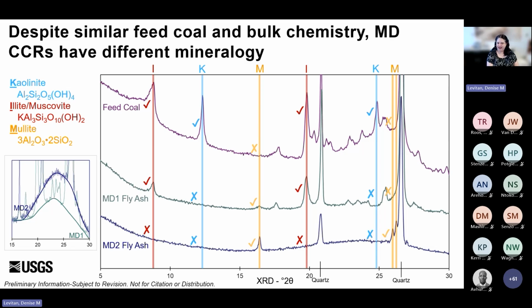So if you look at the blue Ks here and here, I marked with checks and X's whether those peaks are present or absent in each of the diffractograms. So looking at the kaolinite, you can see in the feed coal those two peaks are very clearly present. But then if you look down in the CCRs, the fly ash from MD1 and MD2, those peaks are gone. And this reflects that kaolinite starts to dehydroxylate and thermally alter around 400 to 600 degrees Celsius. So it's present in the coal, but it's thermally altered to something else in the fly ashes.